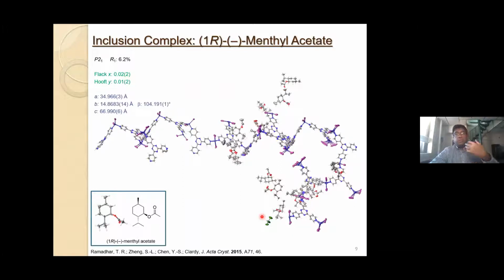Now, I want to show you this asymmetric unit of the inclusion of 1R-menthyl acetate inside the crystalline sponge because it's a special beast. So upon trapping this in the crystalline sponge, there was a single crystal to single crystal transformation where the space group symmetry dropped from C2/c to P21, and the unit cell size, at least the c-axis, doubled in size from 33 angstroms to about 67 angstroms, causing us to get a huge unit cell with a lot of atoms. And actually you have over 500 non-hydrogen atoms inside. So this became like refining a little protein. And it took me about 3 weeks to be able to refine this fully, but I was able to do so and locate 14 molecules of 1R-menthyl acetate in the asymmetric unit.